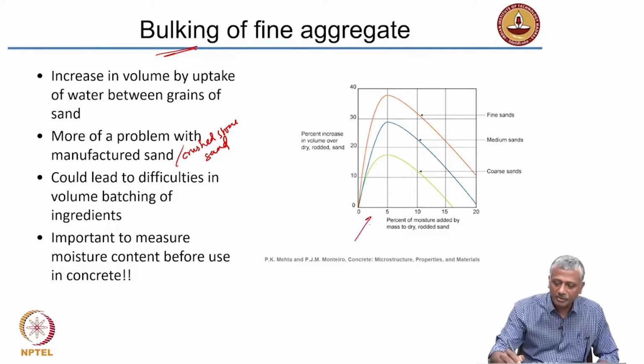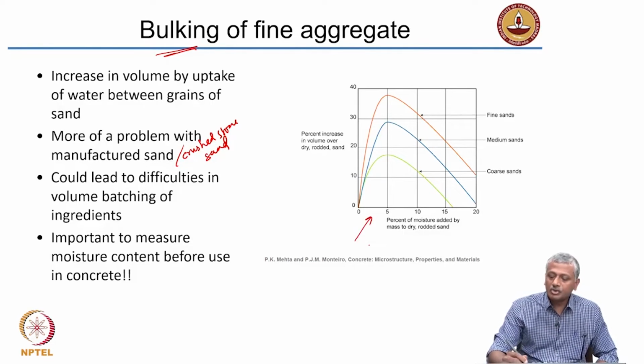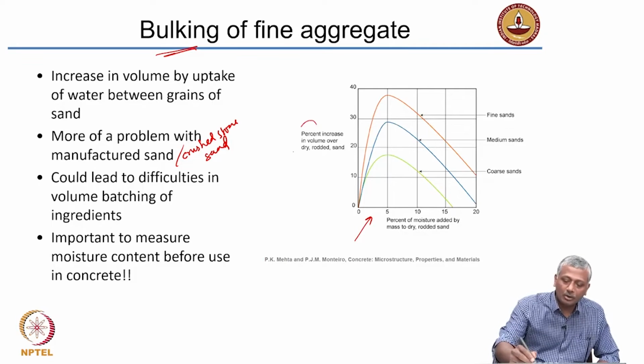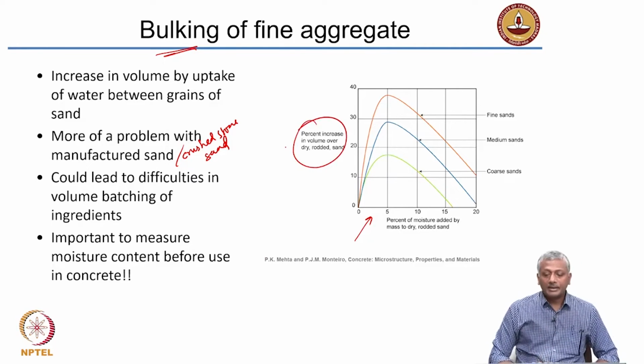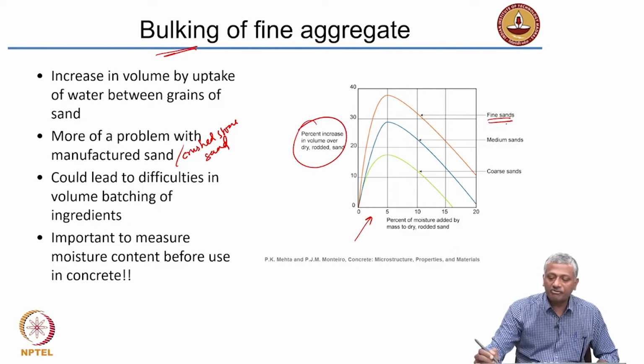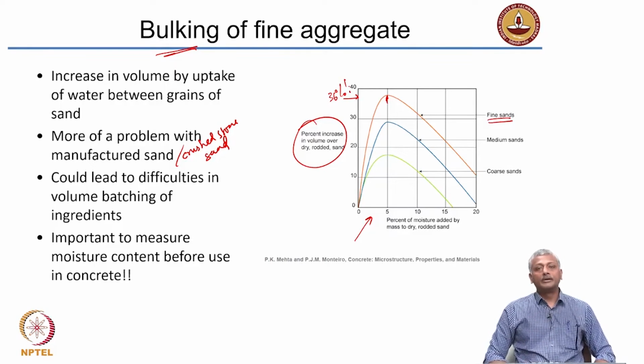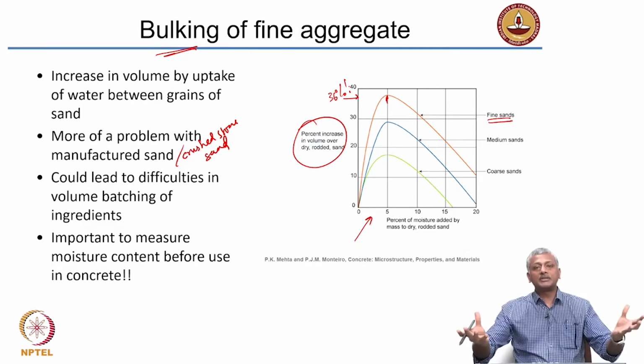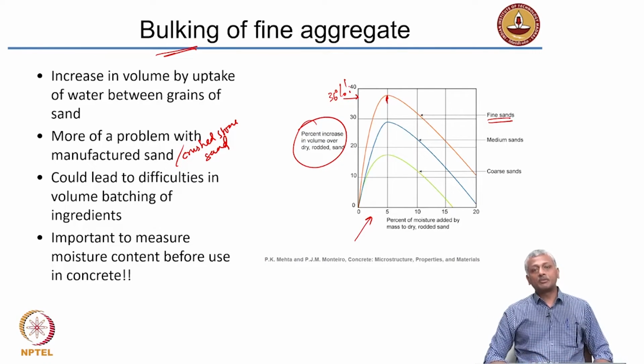Again, this is a picture from one of the textbooks on concrete technology, which shows you that the bulking or percent increase in volume is most affected for fine sands. So, you can see the increase in volume can be as much as 35% or 36% here. Okay. So, if you are thinking you have 1 cubic meter, it is actually 1.36 cubic meter because of the water that is getting inside the fine sand.